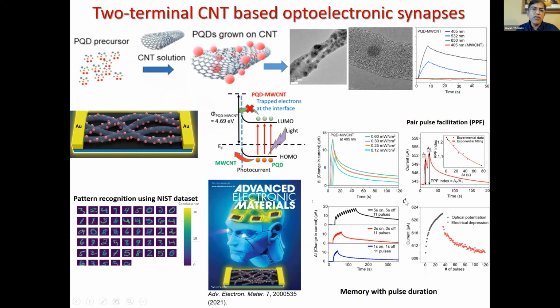But going beyond graphene, we have expanded that work to carbon nanotubes. We can follow a similar approach, growing quantum dots on these carbon nanotubes. Here we developed a two-terminal device with a number of carbon nanotubes. Why we are doing it is that you can go to single carbon nanotube based devices, which may be possible in the future. Here you can see some of the quantum dots grown on carbon nanotubes in the TEM image, and even some of these quantum dots can grow inside the carbon nanotubes.